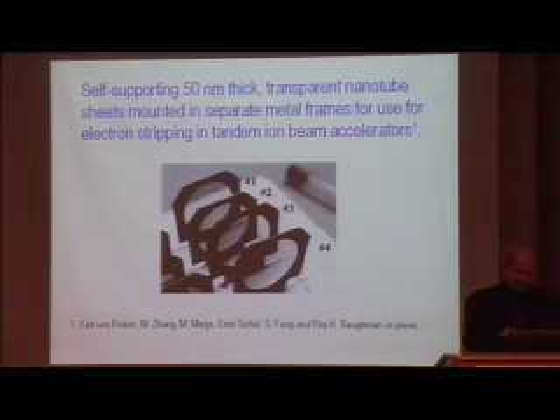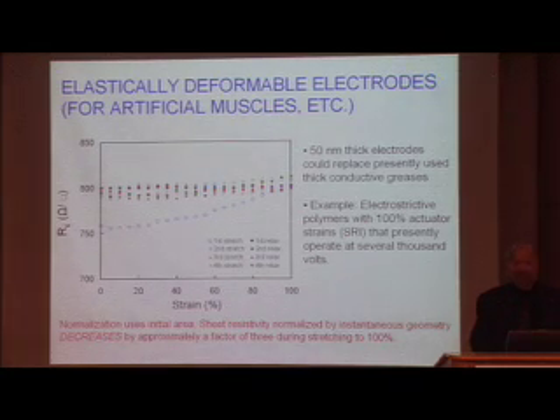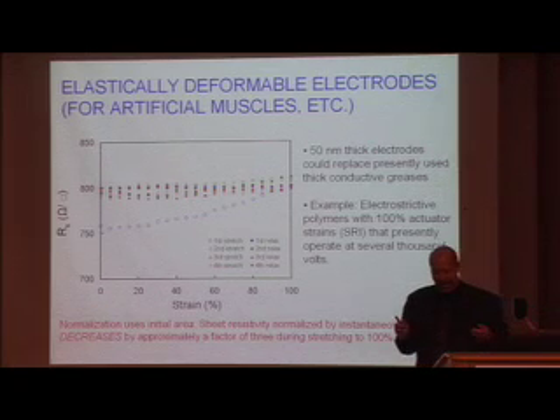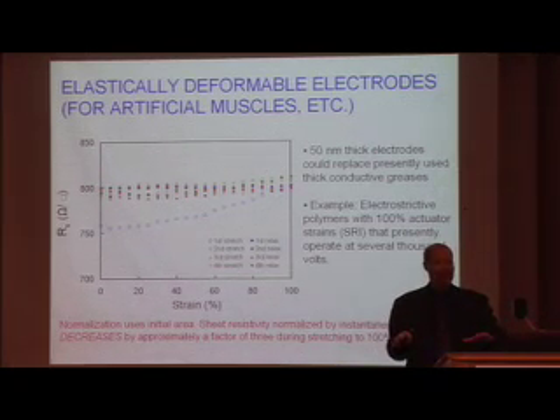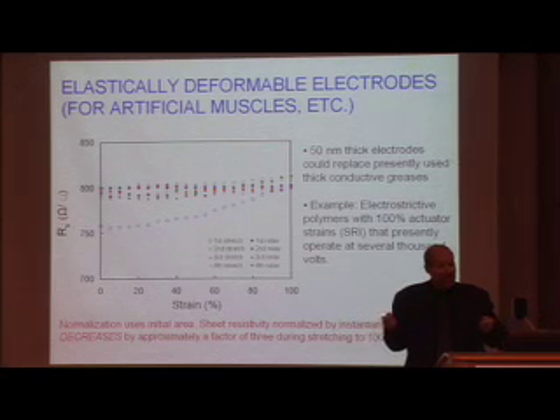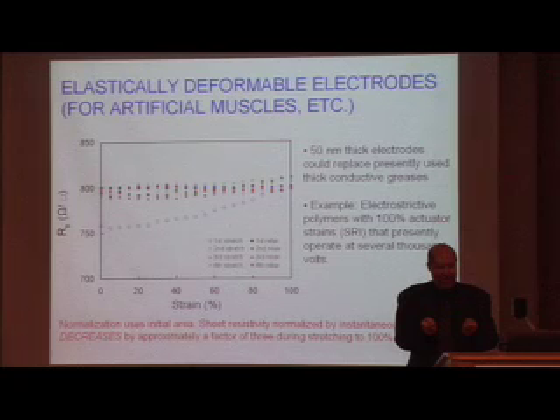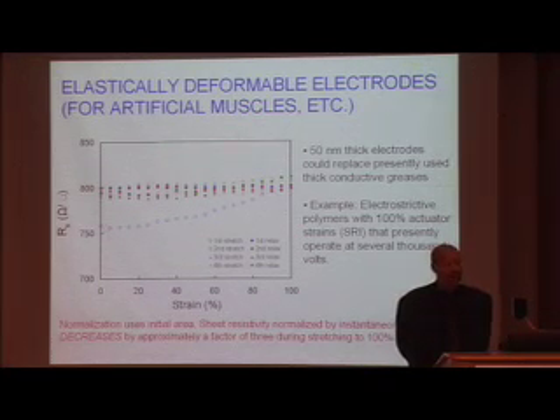We can use these carbon nanotube sheets, even though they're so thin, we can move them around easily, assemble them. We've published a paper on using these nanotube sheets because they are transparent to ions for ion stripping for accelerators. We can make these carbon nanotube sheets so that they are elastomeric. It's a very simple trick. What we do is we take a silicone rubber, stretch it, slap on the carbon nanotube sheet. Now allow the silicone rubber sheet to go back to its original dimension. Now we can reversibly stretch by 100% the carbon nanotube sheet without causing its change in electrical conductivity.